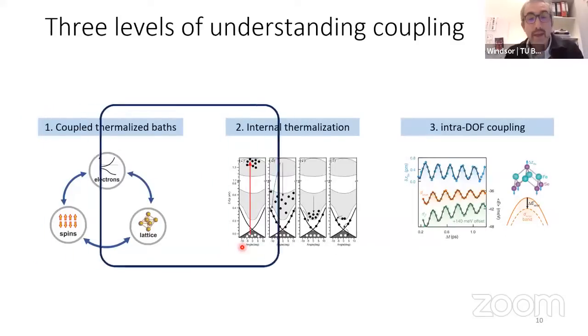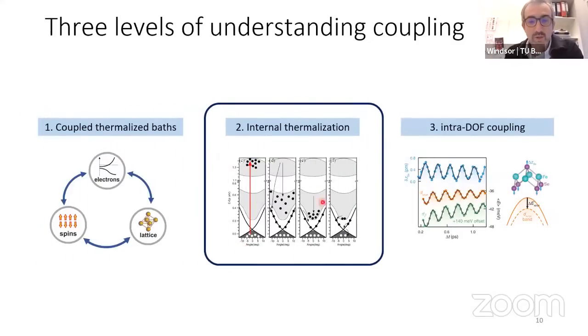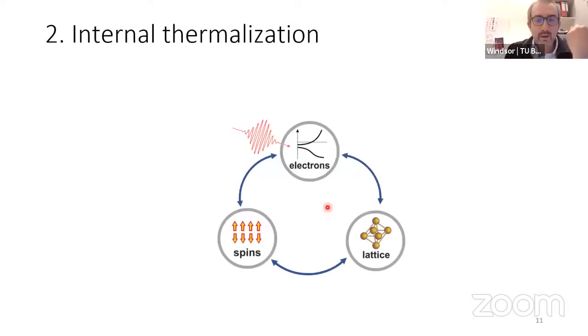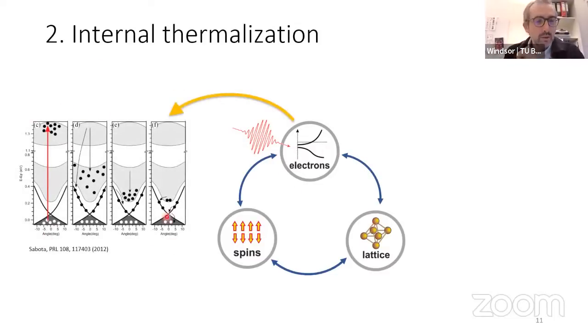And this brings me to the second level of understanding of such couplings, which is sort of the internal thermalization of these degrees of freedom. And so the conceptual understanding here is that there is evolution within these heat baths. So not just transfer of energy from one to the other, but also within them. So we have to break them apart. Here is a nice image taken from this paper from 2012, about 10 years ago, where we have